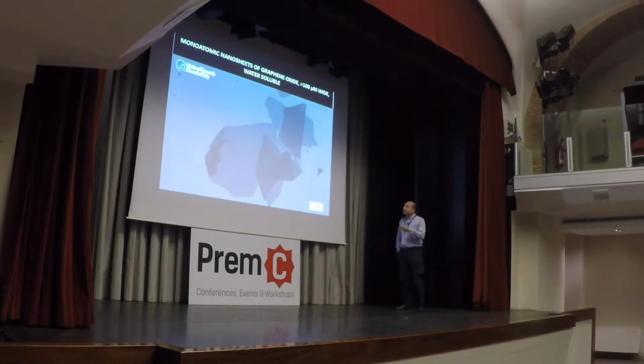You can get tiny amounts of sheets like this with the Scotch tape, so producing graphene sheets one at a time, but all the solutions, all the things that are now even on sale are much smaller sheets of 100, 500 nanometers, not only monolayers, you have lots of multi-layers, and they are never really pure. So there is always some surfactant, some solvent that is difficult to remove.